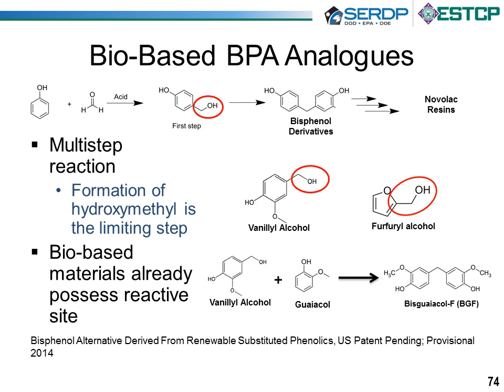And an interesting thing is, there are bio-based molecules, vanillyl alcohol and furfuryl alcohol, that already have that functionality on them. So we decided to use those to make bisphenol A surrogates. And we can see that reaction scheme between vanillyl alcohol and guaiacol, which are lignin derivatives. We're able to produce what we called bisguaiacol F, or BGF, which is very similar to bisphenol A, but, very similar to some of the molecules Ben produced here, has a methoxy group attached to the benzene rings.